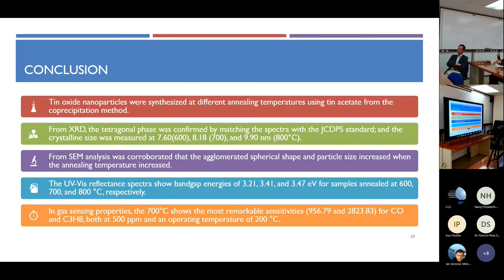In conclusion, tin oxide nanoparticles were synthesized at different annealing temperatures using tin acetate by the co-precipitation method. The crystalline size is around 7.60 nanometers for 600, 8.18 for 700, and 9.90 for 800 degrees Celsius. SEM analysis shows agglomerated spherical shapes, and particle size increases with annealing temperature. The UV reflection shows the band gap increasing, 3.21, 3.41, and 3.47 electron volts, for the different annealing temperatures. And 700 degrees Celsius shows good sensitivity compared to 600 and 800 for both carbon monoxide and propane.